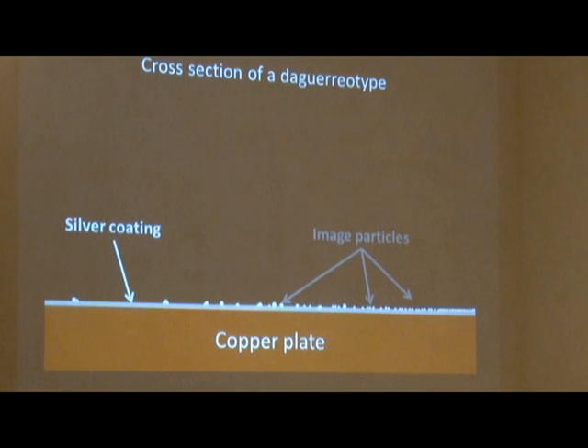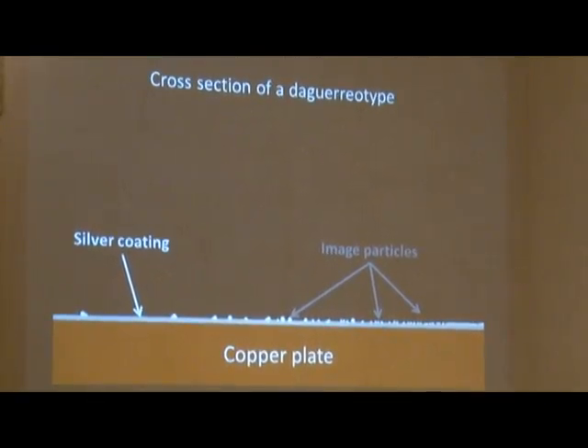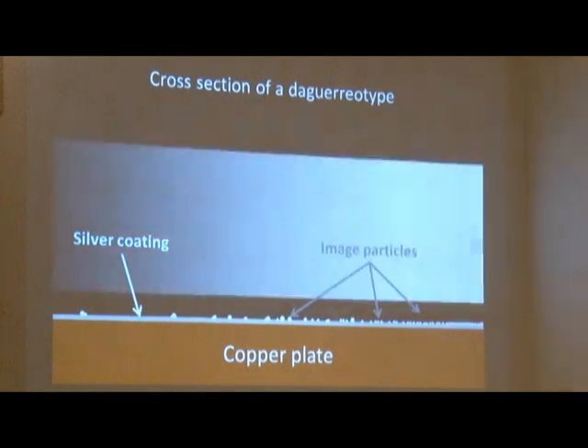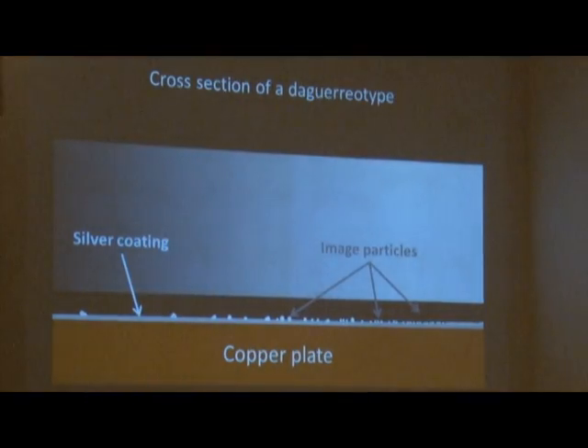The bottom is a copper plate, and on the image side is a silver coating. It's a pretty thin coating. The proportion of the diagram is a little off, but the silver coating is polished by hand to a mirror surface. On top of that are image particles. There are more image particles in the light area of the image and fewer in the dark area. This distribution of image particles gets determined based on the gradation of light to dark when the plate is exposed in the camera. And this gradation makes up an image.